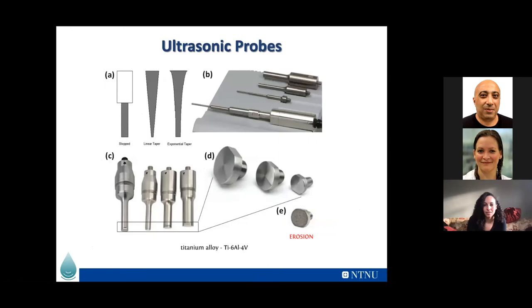The problem when you use a probe is that after a long term of operation, you get erosion, and that could be a big issue when you're inserting your tip directly into your system. This is actually a titanium, aluminium, vanadium alloy. It's very strong, but unfortunately it does erode because of cavitation bubbles impacting the surface.